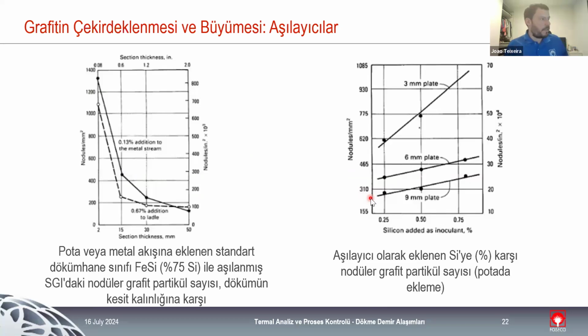And in here is just for us to quickly see the effect of inoculation. In this picture, we can see the nodule count related to the section thickness, and you can see that we have two different types of inoculation. We have metal stream, so late stream inoculation, and we have ladle inoculation, so early stage. And you can see that the nodule count is decreasing with the section thickness. So section thickness being increased means that the solidification time is also increasing.